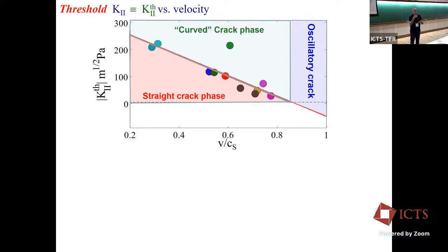We saw that the numerics saw microbranching, but the theory couldn't find it. And why couldn't it find it? Because if we're looking over here for an instability and we're perturbing around there, we're not going to see it. It's stable. We need to give it a large kick to get to the second branch. And it's a hysteretic branch.